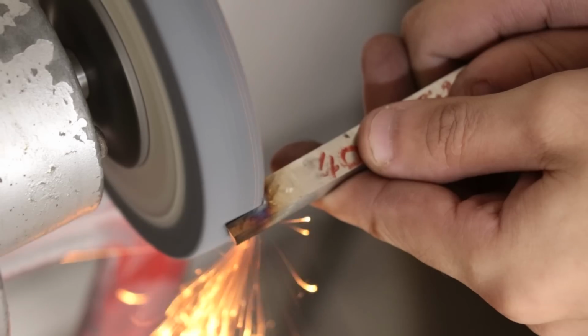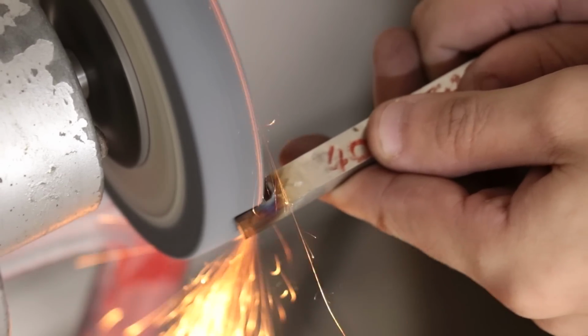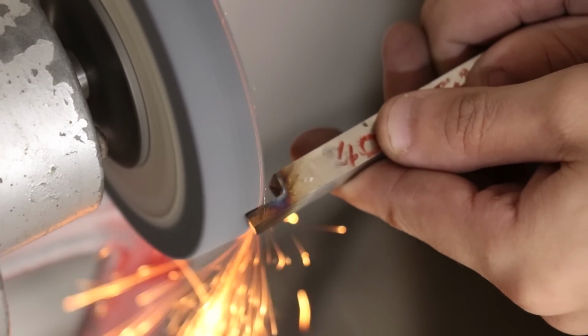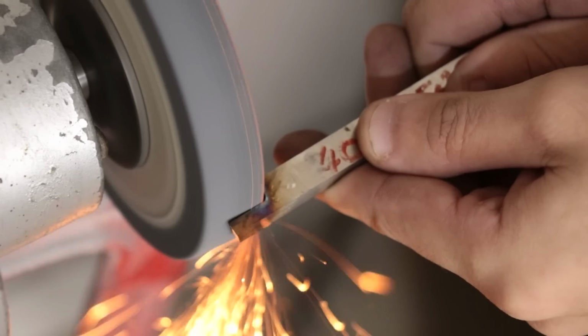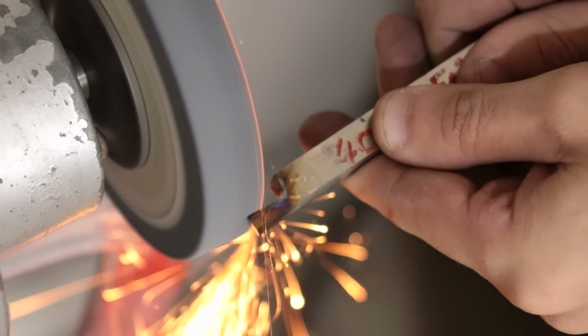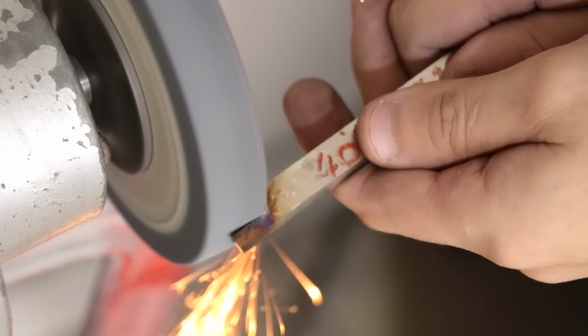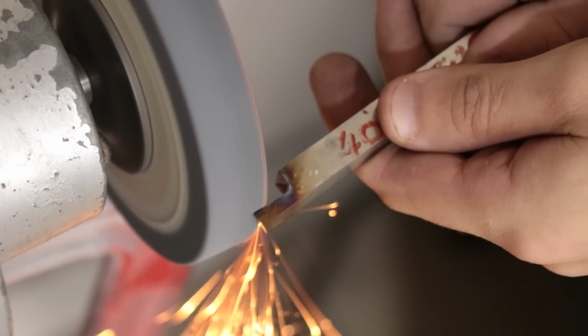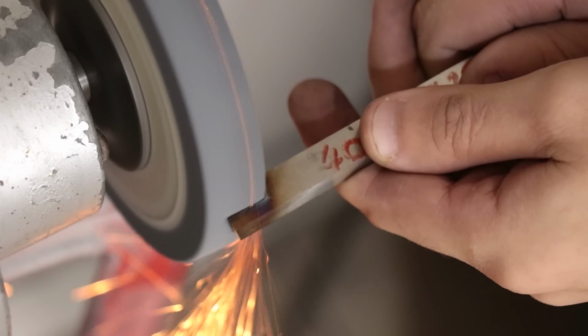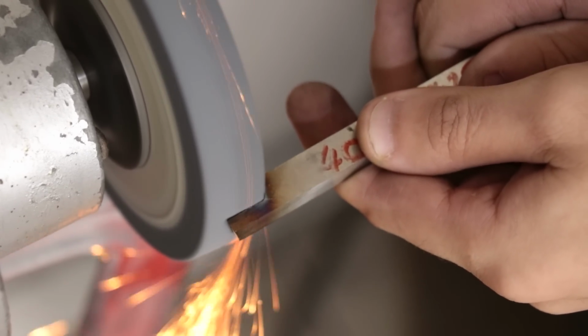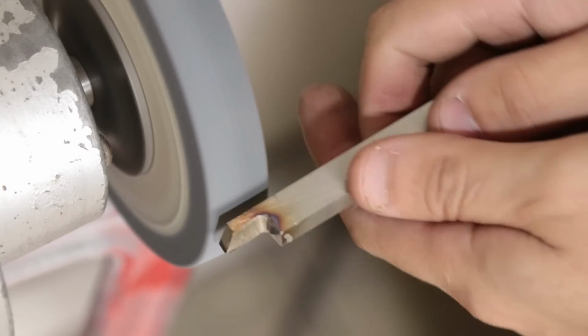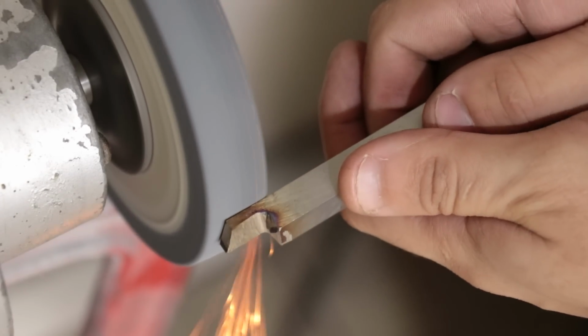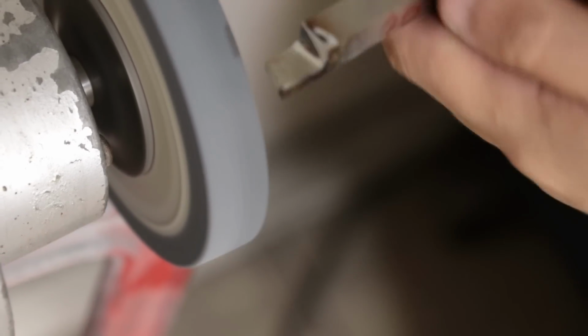High-speed steel is one of these alloys that is able to resist losing its temper at high temperatures, and as a result, when I'm grinding it, say on the bench grinder, if it becomes straw-colored or even starts to go blue, it's not going to be a huge problem. High-speed steel is an amazing material, and you don't tend to lose hardness until you reach about 500 to 550 degrees Celsius, or even higher if you mix in a bit of cobalt. So for the most part, when I'm grinding up high-speed steel, the heat is never a big issue. I've always said that the heat is probably going to hurt you long before it ruins the temper.